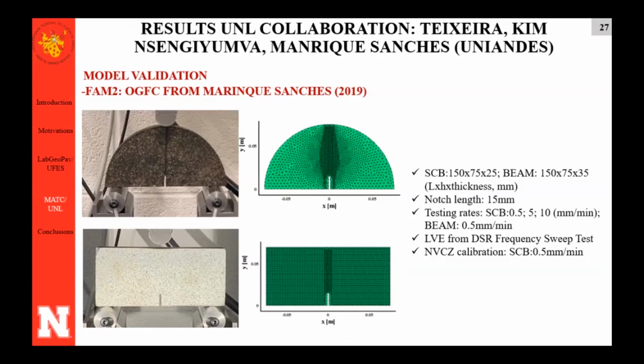Take an SCB test and calibrate for 1 rate. So we calibrate for 0.5 millimeter, and we predict for the 5 and 10 millimeter rates, different rates. And I also try to predict the beam behavior.